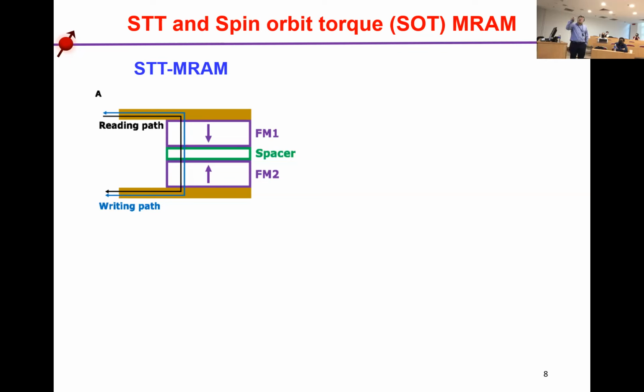Another one, the reading path and the writing path share the same path. Therefore, the spacer layer, which is normally a non-magnetic oxide, will deteriorate after many cycles. So the endurance becomes a problem. So the disadvantage of STT-MRAM is the endurance problem. And another one is the speed, because we need to increase the temperature, which takes some time.